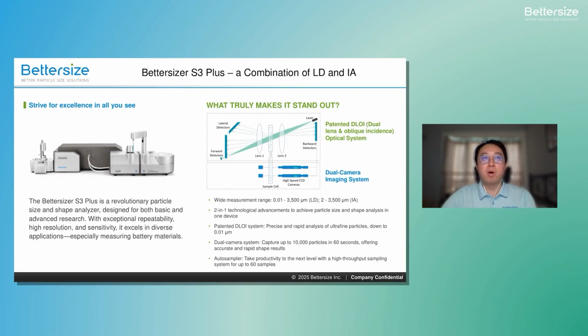For the LD part, the Bettersizer S3 Plus is equipped with a Bettersize patented dual lens and oblique incidence design system to ensure the accuracy of measurements, even for the finest particles down to 0.01 microns. For the image analysis part, the Bettersizer S3 Plus has a dual camera system to rapidly and accurately capture flowing particles.